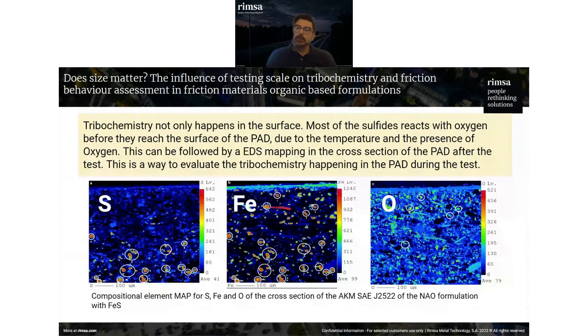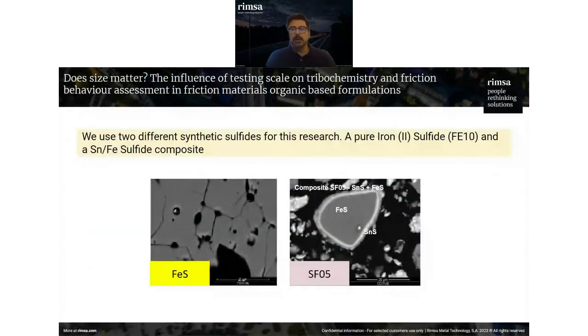So to some extent, this iron sulfide has been reacting beneath the working surface, and has become iron oxide. So if this happens on the dynamometer, it's very important that this also happens on the tribometer, the pin on disc or whatever lab scale tool you use to assess a friction material, in order to guarantee that the results we are getting for the coefficient of friction, the engineering results, are going to be easily correlated with the results we may obtain from big testing equipment like a dynamometer. So you are going to see a brief comparison with a formula.